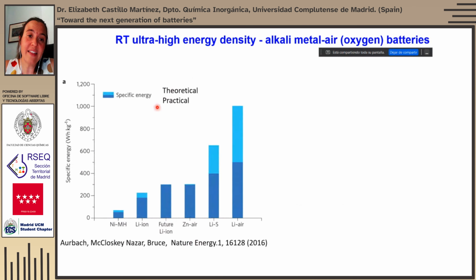If we were to compare the theoretical and practical specific energy in watt-hours per kilogram of different battery chemistries, we see that the lithium air is by far the one that shows the largest capacity. But also, if we consider the contribution from all the external components like casing and current collectors, the practical capacity is not that much. Nonetheless, the theoretical capacity approaches that of gasoline. And that's why lithium-air batteries are in the spotlight for making it into electric vehicles.